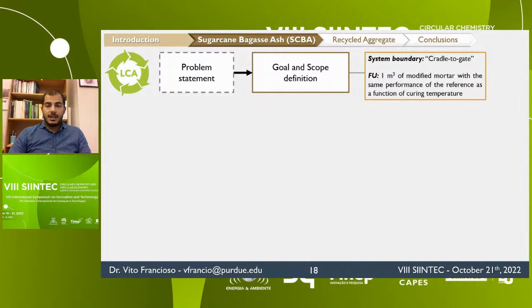The system boundary that I chose for this study was cradle to gate, so from the production of the material to the point that the material is then sold. And the functional unit that I chose for this study was 1 cubic meter of mortar with the same compressive strength as the reference mixture, so the mixture with plain Portland cement and without ashes, and cured at the same curing temperature.